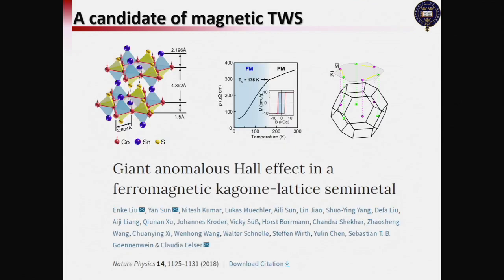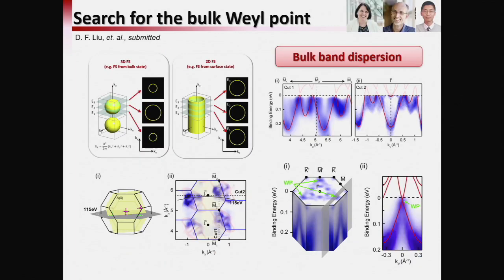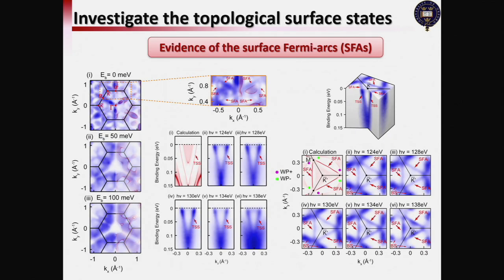And there's recently a good hint on a candidate. It's cobalt tin sulfide, which shows the anomalous Hall effect. Then we thought that was a good one, and the calculation does show there are six Weyl points here. And we used our old technique. We measured the bulk band structure first to locate the Weyl points, and then we also identified the surface Fermi arc that connects these Weyl points. Then we showed that this can be a time reversal symmetry broken Weyl semimetal.